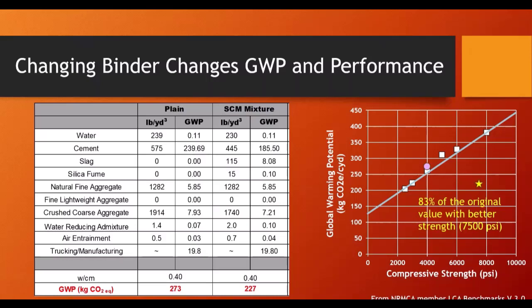All right, it was mixed and designed before people were super excited about global warming potential. But the big thing I would tell you is this dropped the global warming potential by about 17%, very similar to what Tom saw. But in doing that, we also got a very substantial increase in strength. We went from around 4,000 psi to around 7,500 psi. We're now at that little yellow star over there on that graph. So, a reduction in GWP, but we moved over.